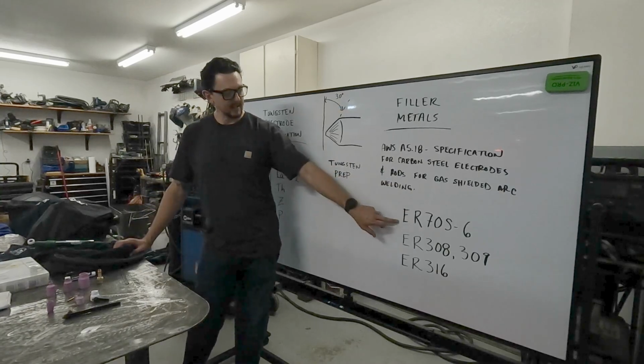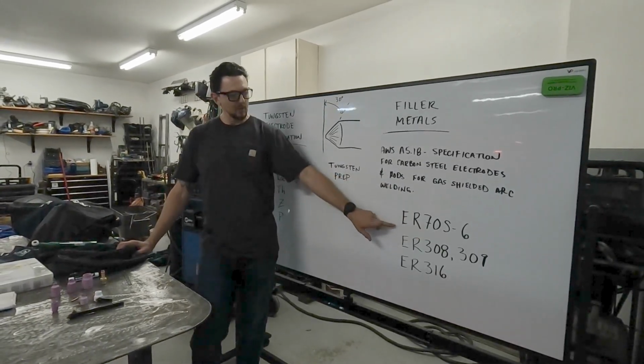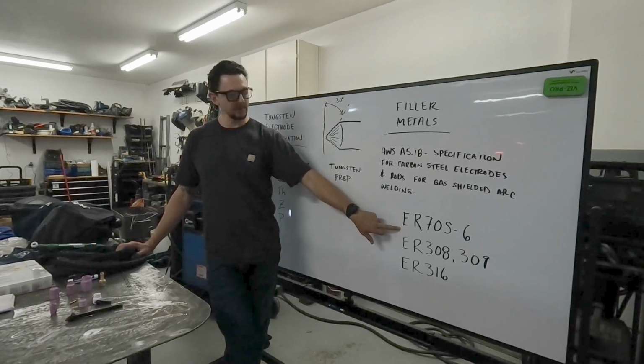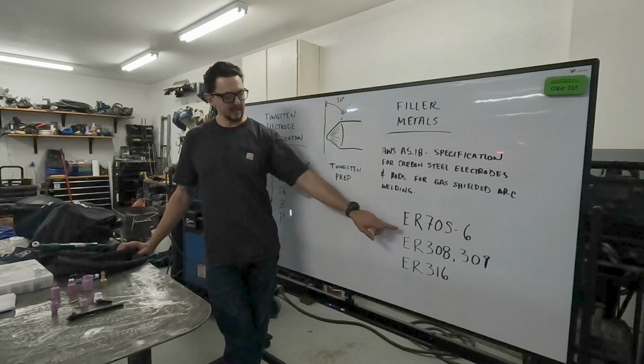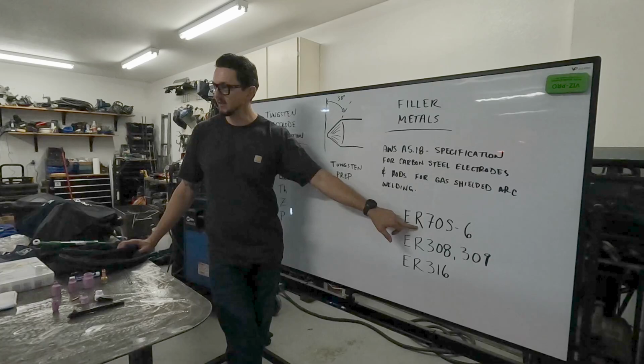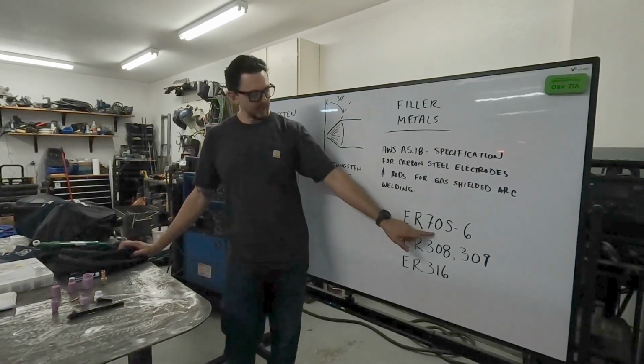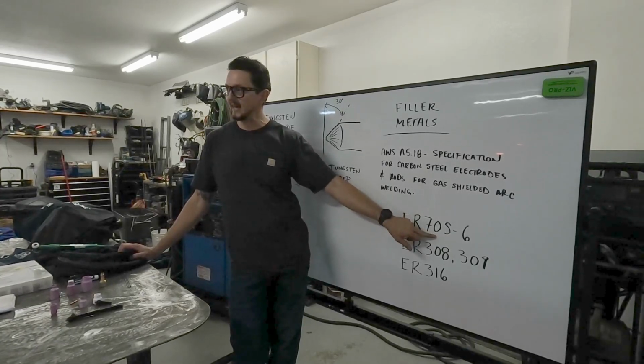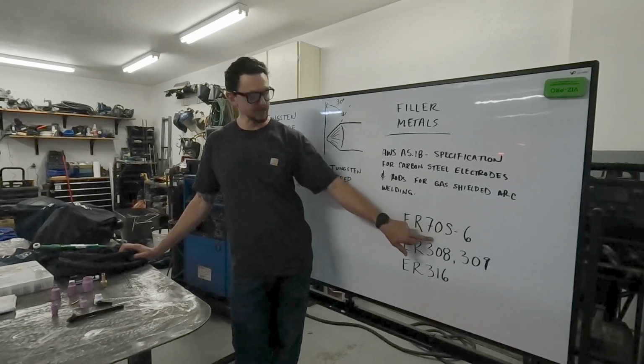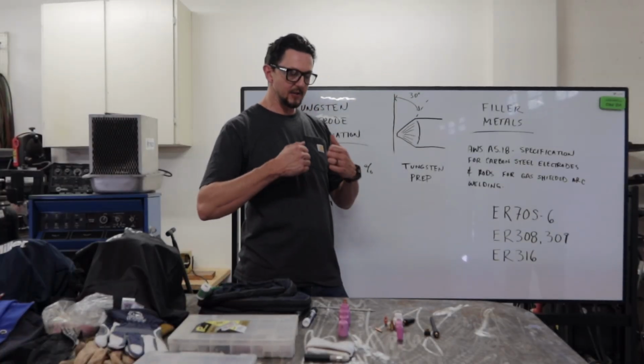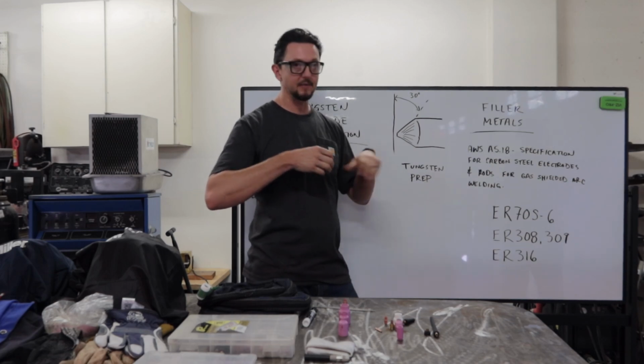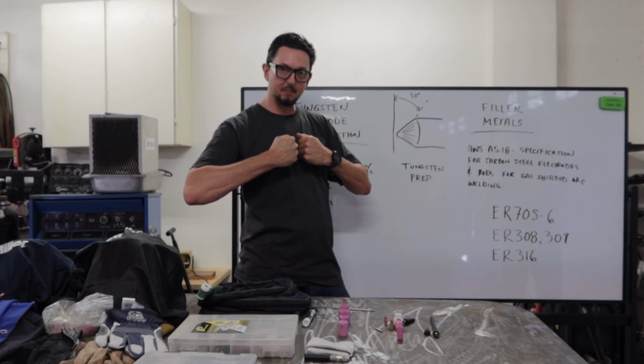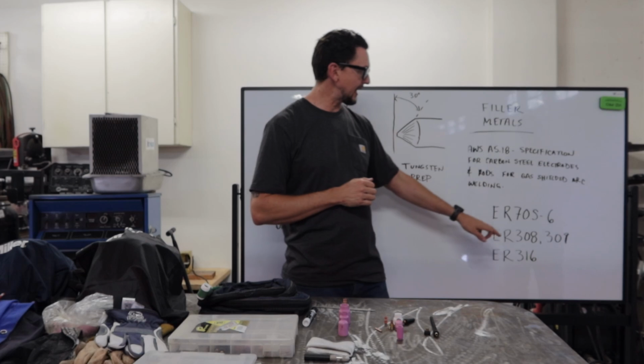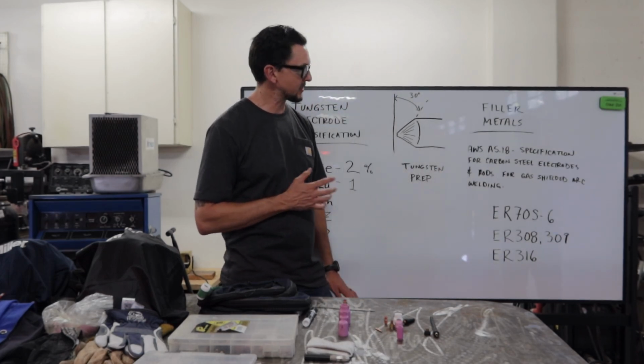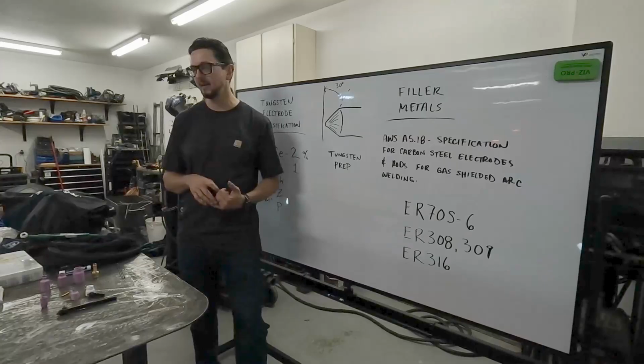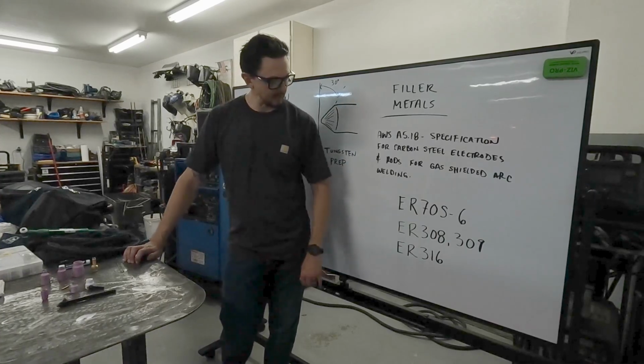So A5.18, the classification system looks like this. We have an E, which is electrode, current carrying electrode, or rod, ER, right? So it could be a wire electrode, or it could be a pre-cut length of rod, either one. The next two numbers here is the tensile strength in KSI, which means thousands of PSI. So this would be 70,000 PSI tensile strength. So that's the minimum amount of tensile strength that this weld metal, this filler metal has in terms of when they pull a sample of it to failure. It will have at least 70,000 tensile strength, okay? And that's really important to be able to overmatch the material that we're welding on. So again, 70,000 PSI.